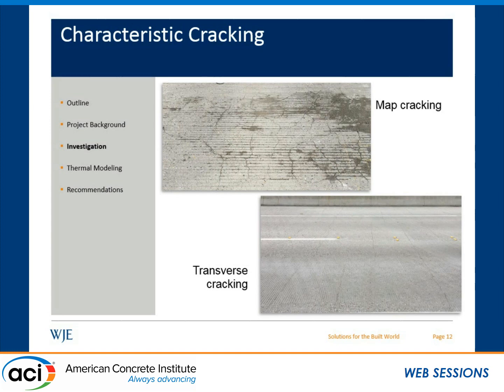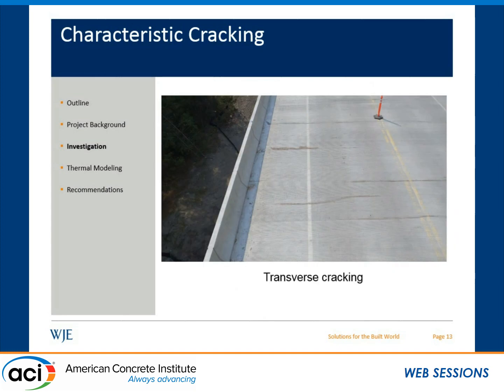If it's not, it'll be much more apparent on the next slide. But we saw much more frequent transverse cracking on a number of these decks, approximately 2 to 4 foot spacing at the worst, though in some cases they were as closely spaced as 6 inches from one another. This particular bridge that I'm showing here is 1 year old. The cracks are actually sealed, which makes it easier to visualize. These sealants were applied within the first month before the bridge had even opened to traffic, and all of the sealed cracks were 10 to 15 mils, 10 to 15 thousandths of an inch in width. So pretty wide cracks. They were spaced about 2 to 4 feet in some cases on this bridge that's only 1 year old.